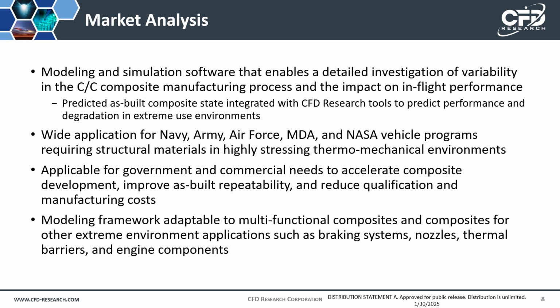These carbon-carbon composites are primarily used for aerospace applications because they are one of the few structural materials that keep their strength at temperatures encountered in re-entry and hypersonic flight. For the government agencies, prime contractors, and material vendors addressing these applications, our models can help speed up composite material development by cutting the number of build and test samples. By showing what material specifications and processing settings are most critical, the model results can help improve repeatability of the as-built material. Since repeatable samples are critical to getting useful information quickly during both ground and flight tests, accelerating this part of the development and insertion cycle will reduce qualification costs.